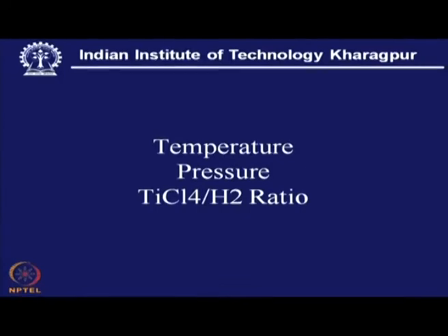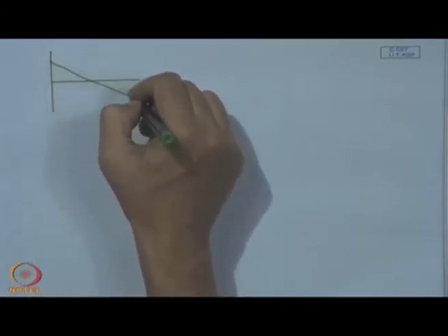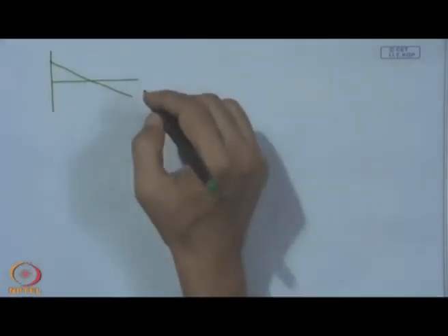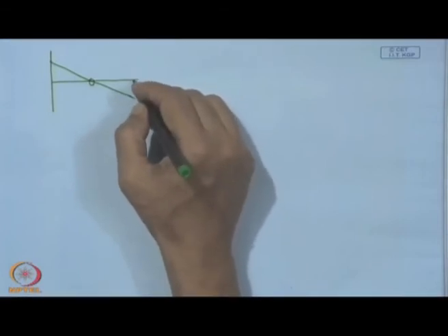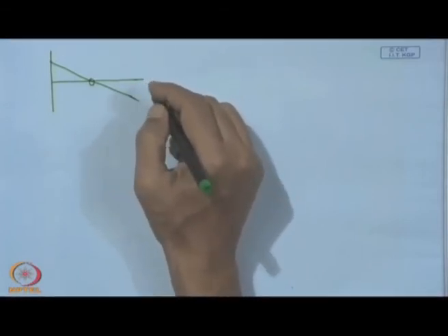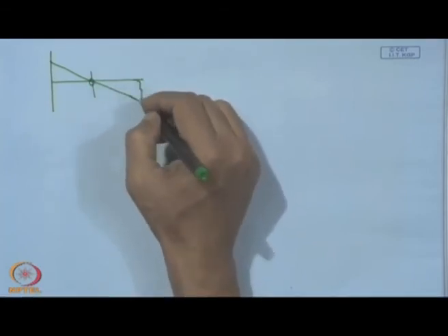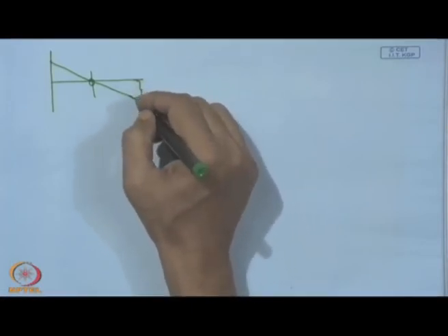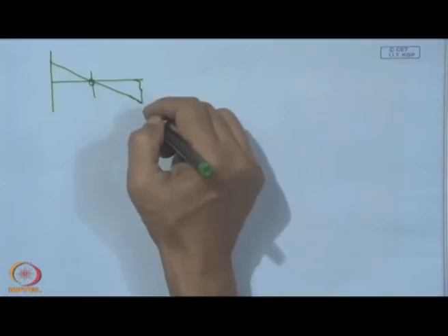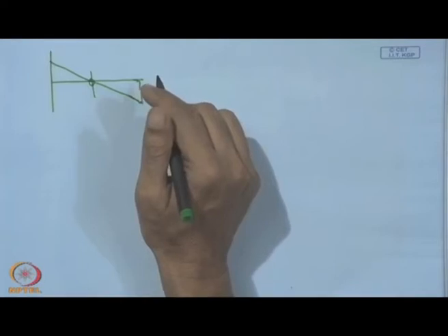Now, the role of temperature can be well understood, because from the graph of delta G variation with temperature, we understand that this reaction is not spontaneous, and we have to really cross this threshold value to have a substantial negative difference, so that the reaction can proceed in the forward direction and it becomes really a product favored reaction.